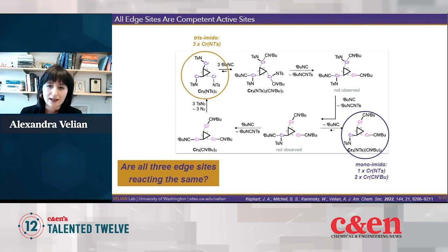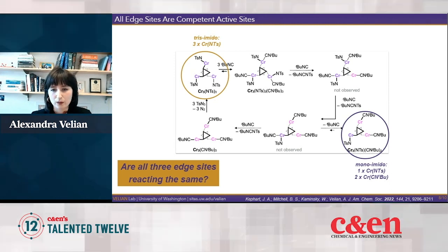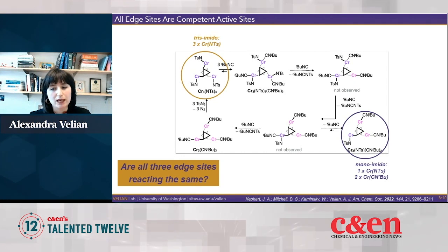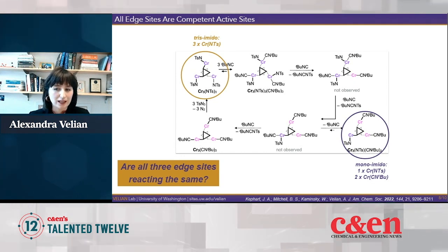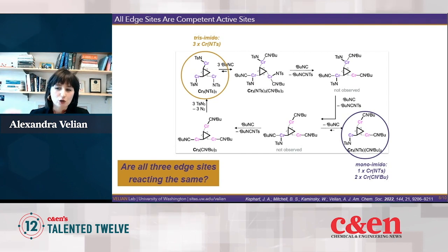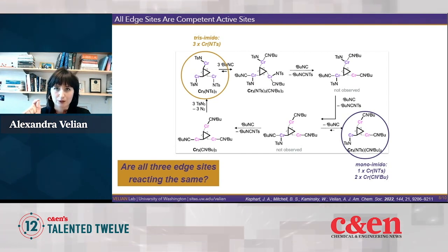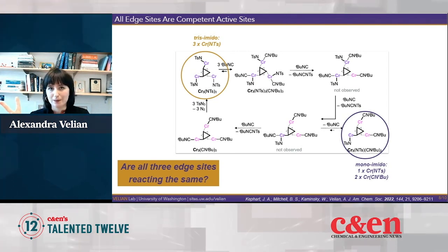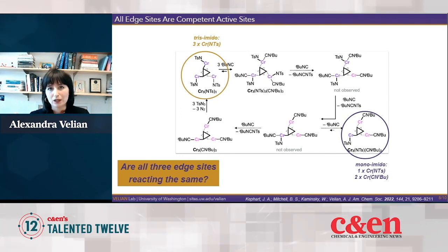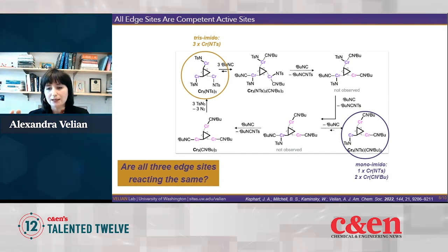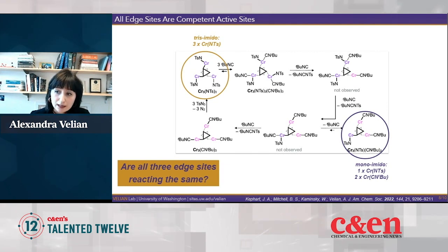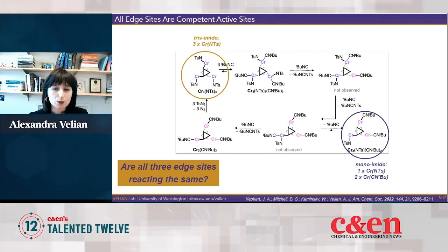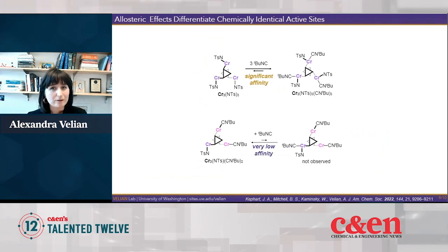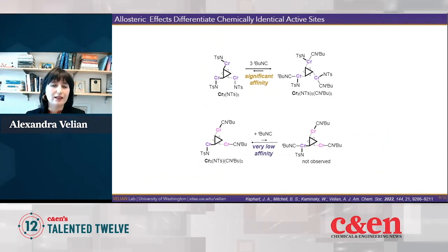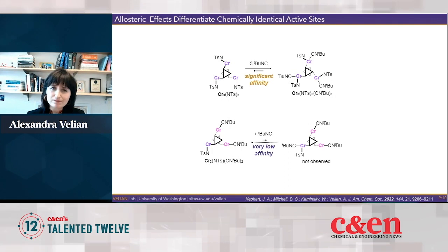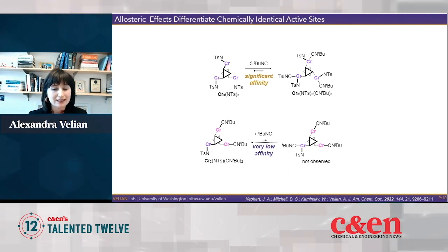There's some interesting stereochemistry going on there that I won't get into, but on the right side, we can also isolate a similar related cluster that features only a single chromium imido on the cluster surface, whereas two of the three chromium edges are now engaged only with isocyanide, right? So this enables us to make a direct comparison in the reactivity of these two species. If there's no connection between the active sites, then they should react the same. But that's not what we find.